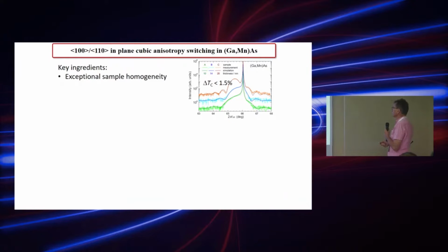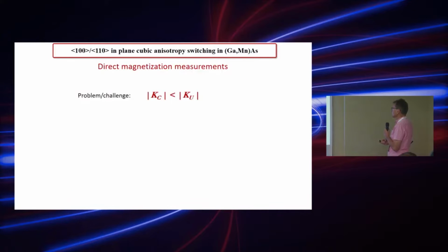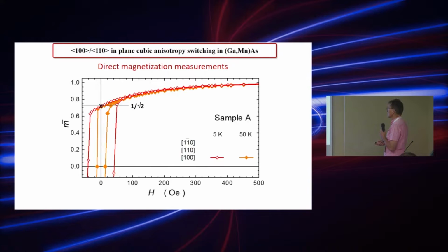However, we regarded this finding as not really conclusive, so we wanted to find direct magnetization measurement evidence that such a change indeed took place. And the main challenge is that the cubic anisotropy constant is, as I said, an order of magnitude smaller than the uniaxial one, so the experiment has to be performed in such a way that we can see this change. So we are hunting the change of the behavior along the 100 orientation, and from FMR we knew that there should be a difference between 5 Kelvin and 50 Kelvin.